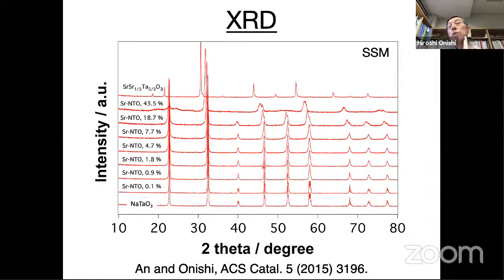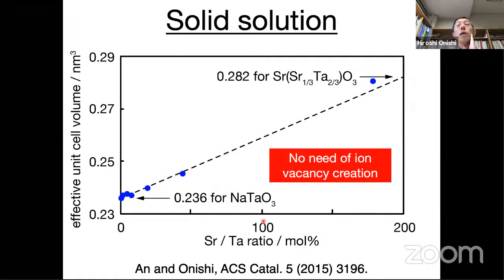So this is X-ray diffraction, a very fundamental way to know the lattice size of the sodium tantalate. And this is the diffraction patterns. And putting strontium into sodium tantalate, the diffraction peaks shifted to the low 2 theta direction. So this means that putting strontium into sodium tantalate, the crystalline lattice expanded. A larger lattice presents a small 2 theta angle for the diffraction peak. And we quantitatively analyzed the unit cell volume determined from the XRD as a function of strontium doping concentration.